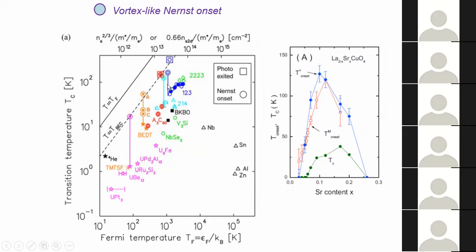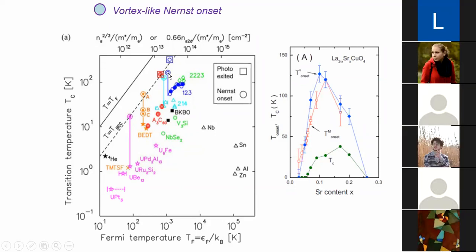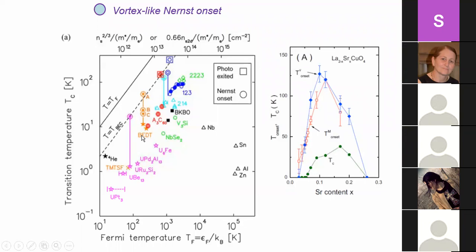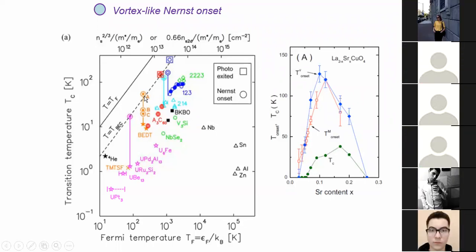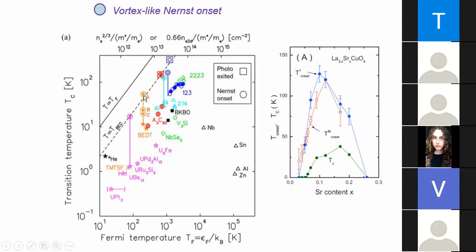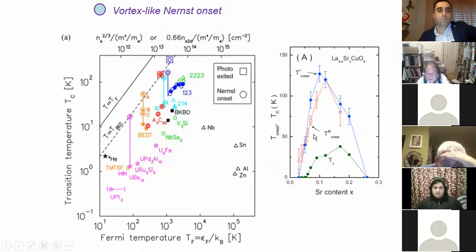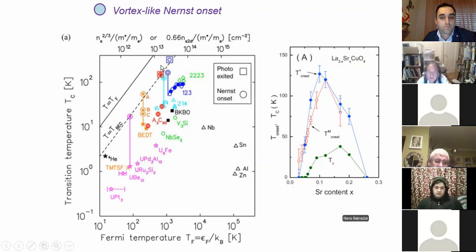And there's another system called YBCO, and the point comes here. There are some two-dimensional organic superconductors called the BEDT family, and their onset of the Nernst effect, in some of the materials, comes here. And in some of the heavy fermions, you see the Nernst onset is here. So this Nernst effect seemingly is giving actual physical phenomena that correspond to our hypothetical dotted line, where we expect this Bose condensation to happen if pairs are already formed at even higher temperature than this. So that means this dotted line is not only a hypothetical, theoretical line, but there may be some real observed phenomena coming on this line.